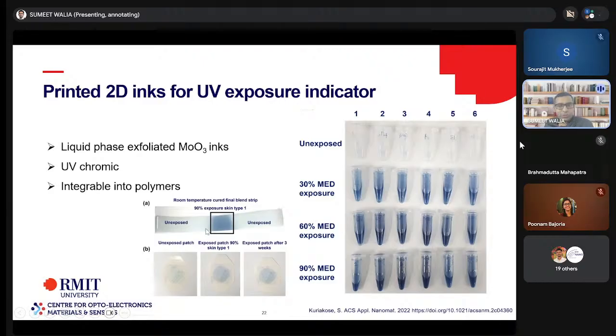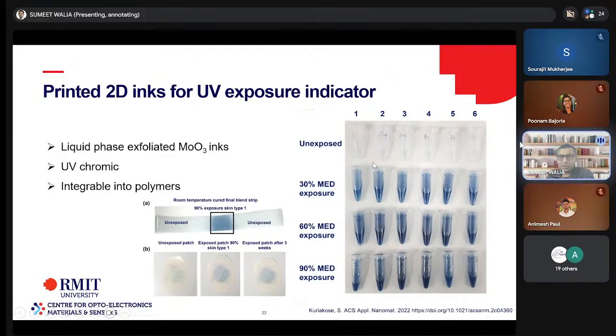Australia has a huge problem with skin cancer, or skin carcinoma, and what we did here is basically prepare molybdenum trioxide inks. As you would see up the top, generally speaking, they're visually transparent, but then we benchmarked it to the Fitzpatrick table for 6 different skin types, because the UV tolerance threshold is different for different skin types. Then we integrated that into a polymer matrix and put that on a 3M backing tape.